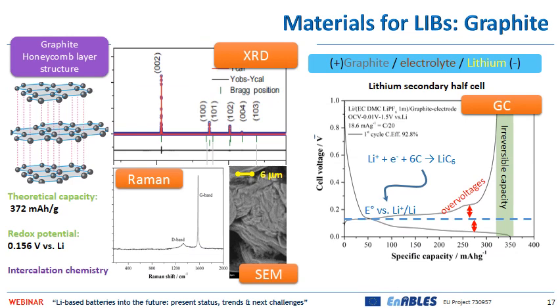If we tackle and break the ice with the state-of-the-art negative electrode material, that is graphite, we can see that graphite has a honeycomb layered structure formed by layers of graphene sheets stacked along the C direction. This material is able to intercalate and deintercalate lithium ions through the so-called intercalation chemistry reaction. An intercalation reaction is a reaction in which ions are inserted into 2D layers that are breathing and are not destroyed due to the reaction.